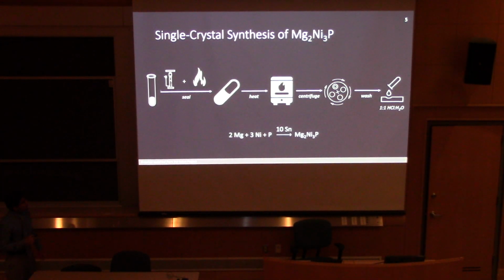We then seal it. Sorry, before that we actually add a piece of quartz wool as a strainer, right? So when we separate out the liquid, the only thing that's remaining is our crystal, and all the liquid has actually settled on the bottom. We then seal it, and then subject it to a heating cycle, which I'll be explaining in a sec. And then we centrifuge out, mechanically, any sort of remaining tin flux. And then in order to get rid of any remaining tin that has settled on the surface of your crystal, we then dilute it in HCl.